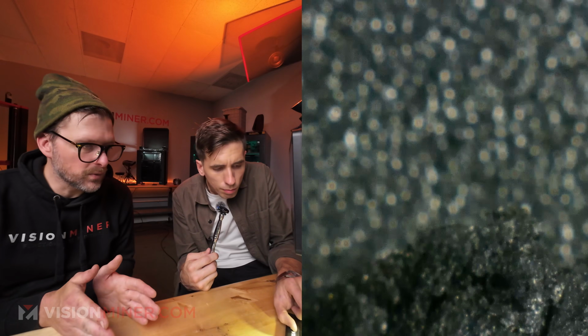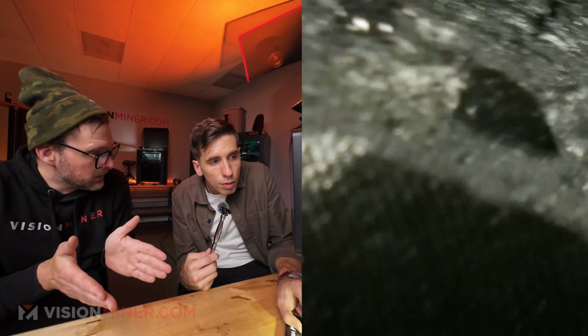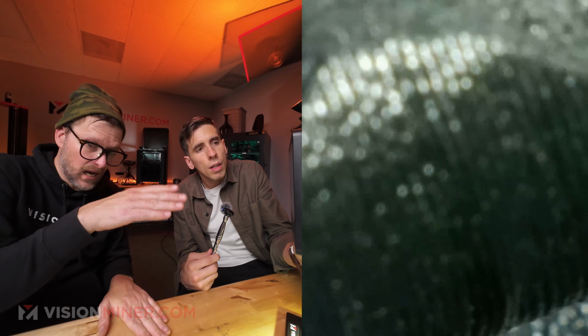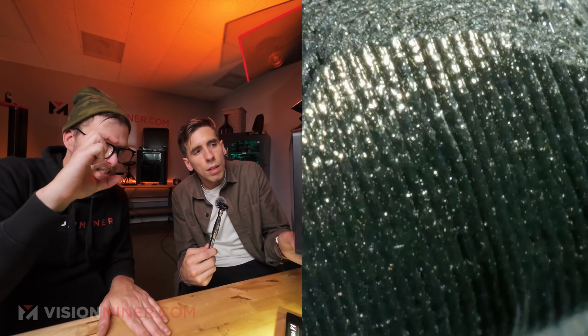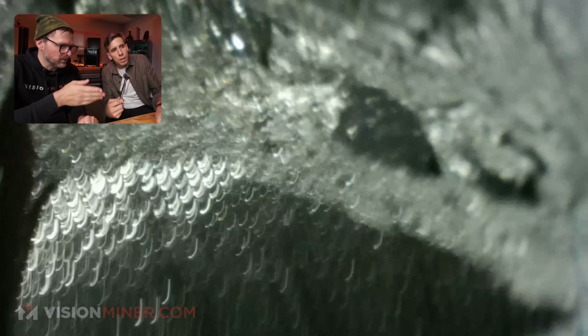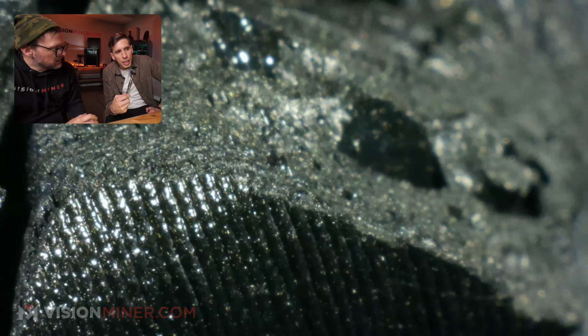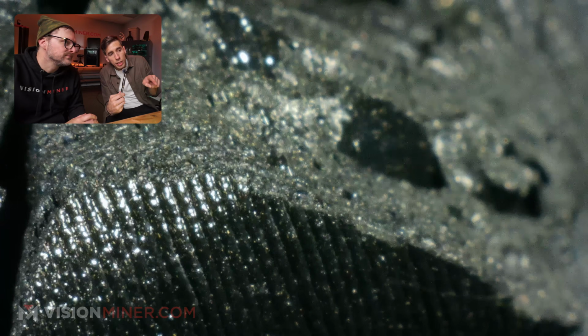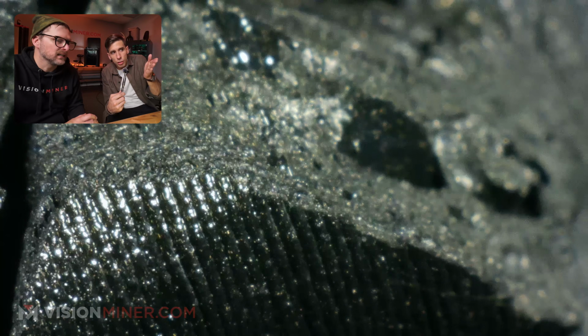Normally you'd be at about 40 to 70% of the strength in the Z. If it weren't printed properly, you'd see it break usually along a layer line or something, correct? You wouldn't see it break like this. These are printed up and down, so it's all Z. It broke laterally instead of... I mean, yeah, you can see it going straight down the layer lines there, and when you look in there, you're not seeing any layers.